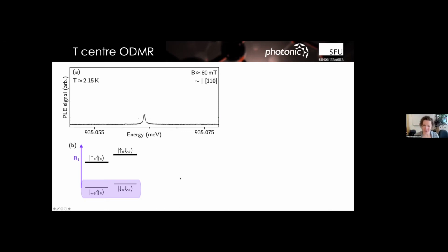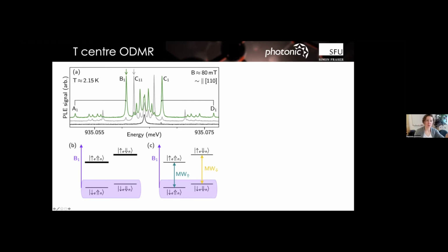Everything else is hyperpolarizing. So if you depolarize, right, if you're probing this with magnetic resonance in this instance, you can depopulate and start to recover some of the signal. And so that's one of the ways that you can tune up your microwaves. So you can start to see that structure again, and you can optimize your microwaves to optimize the signal for one of the orientations over the other one. And so we did take a look at spin lifetimes in this one ensemble here, but we could have optimized and gone for orientation 11 just as well.